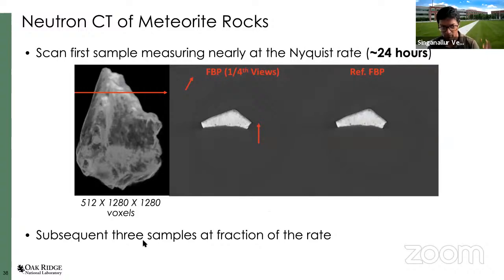So this is an example of a meteorite where we took one meteorite scan, scanned it, retroactively subsampled it by a factor of 4, and we have pairs of low quality and high quality reconstruction. Low quality reconstruction has a lot of streaking. And of course, the reference filtered back projection method, because it's densely sampled, is actually pretty good. You're looking at a cross section of the rock. We actually acquire it fully and then retroactively subsample to show the data.